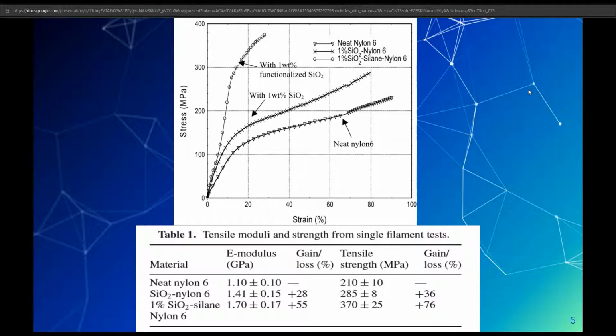In this graph, we can see a strain is put on the standard nylon and it begins to stretch and then breaks just over 200 megapascals. On the other hand, we have the infused silica, which as a strain is induced, the filament resists stretching and breaks close to 400 megapascals. This difference is quite significant.